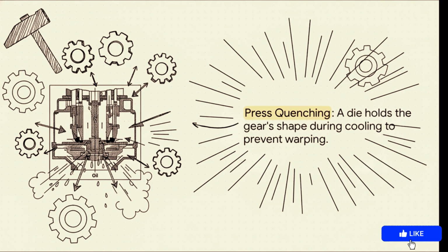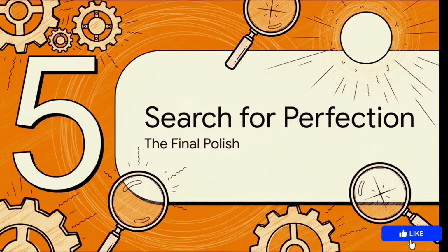So how do engineers fight back against this? Well, one of the cleverest methods is called press quenching. Instead of just dunking the hot gear into a tank of oil, they place it inside a special die. This die physically clamps down on the gear, holding it in shape with a ton of pressure, while carefully aimed jets of oil cool it down. It's basically a way of forcing the gear to stay straight while it's going through that really violent transformation on the inside. But even with clever techniques like press quenching, some tiny distortions can still sneak through.